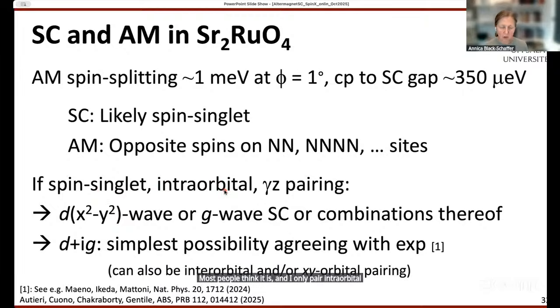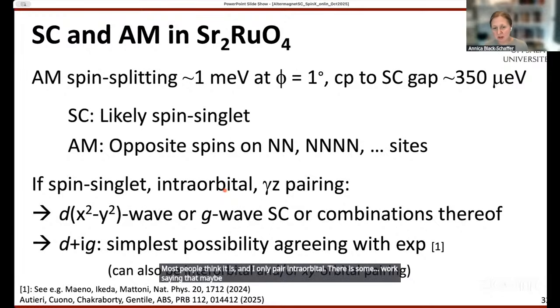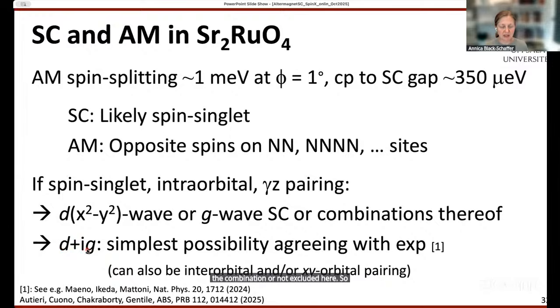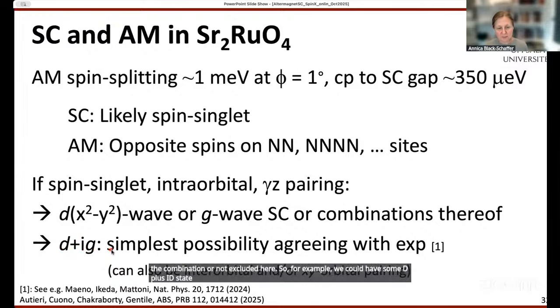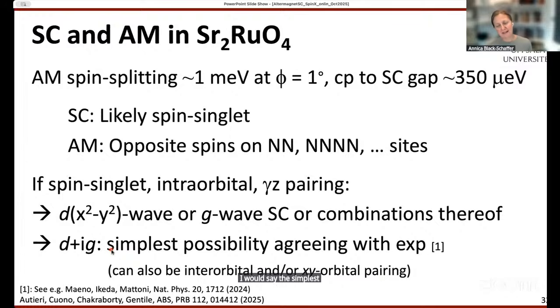There is some work saying that maybe one should pair between orbitals. And I only pair in these two orbitals, the ones that are sensitive to altermagnetism. These are all very reasonable assumptions, and many people make them. Then I can have this d-wave state, the d x squared minus y squared, or higher harmonics, or any combination of them; the combinations are not excluded here. So for example, we could have some d plus ig state, which is, I would say, the simplest possibility that seems to agree with most experiments.